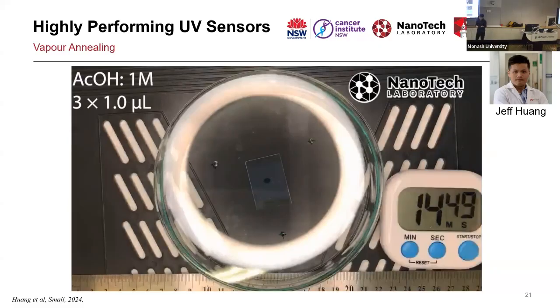And because it is very porous, this time the HAB is 30 centimeter, because we cannot put a droplet on the HAB of the 30, even the droplet on the side will wash away the film. The film is extremely fragile. The black one is just a tape at the back, and then you see 3 droplets inside the chamber. So what you see, you're actually looking at from the top view, and is a time lapse, so it's a kind of a very fast one.